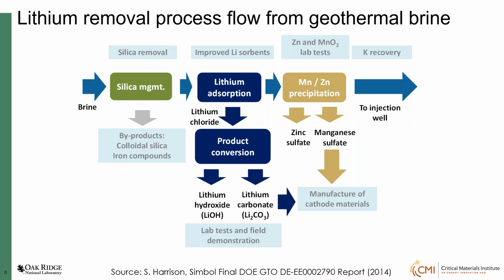But what we were looking for mostly, through the Critical Materials Institute, is lithium removal from the geothermal brine. The brines come out very hot. They have to be kept at 125 degrees Celsius so that all the salts stay dissolved. So we have to use pre-silica management. You can use nanofiltration for pre-silica removal. Then we focused on lithium adsorption. Next slide, please.